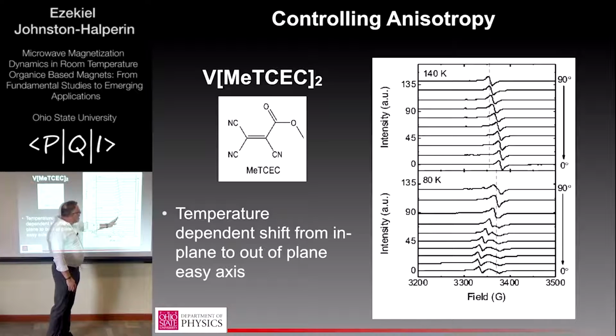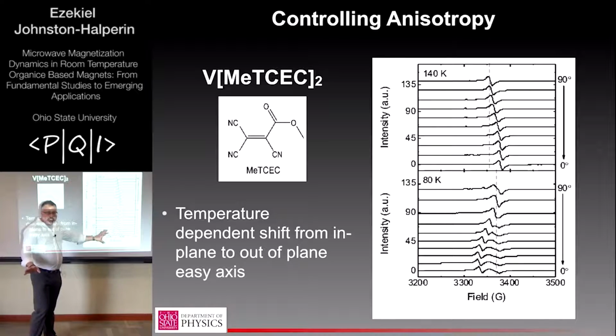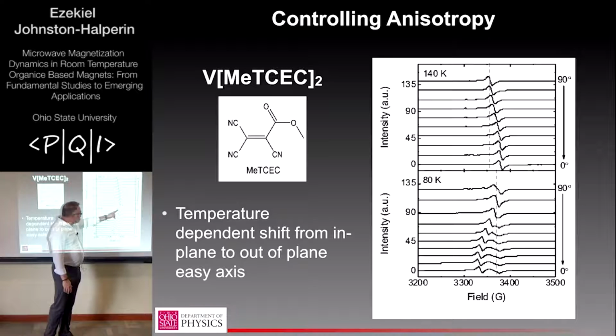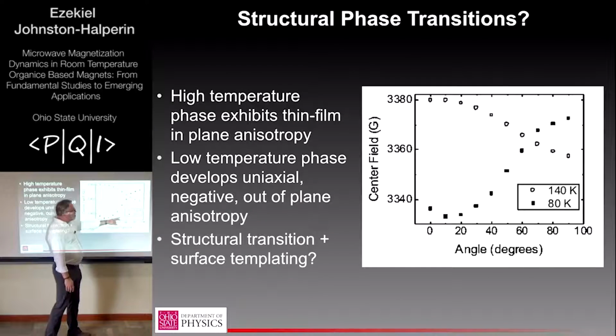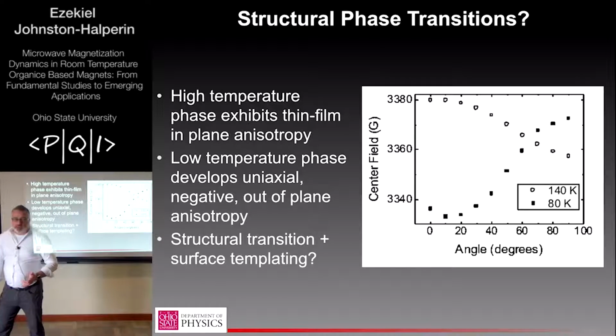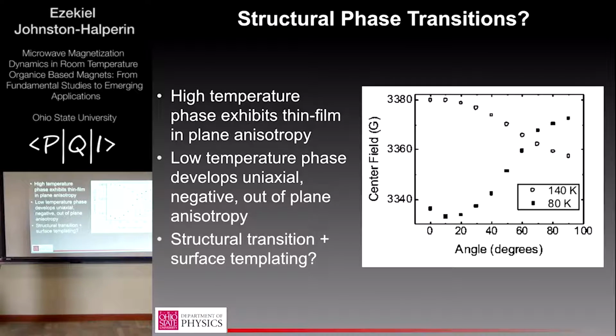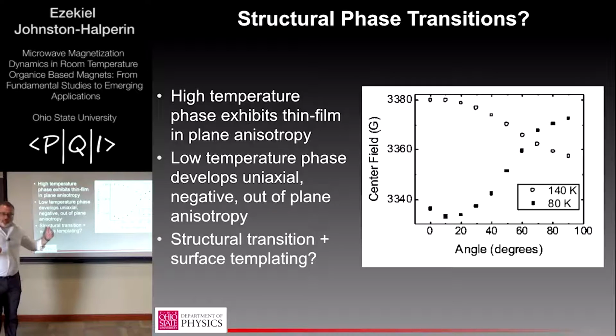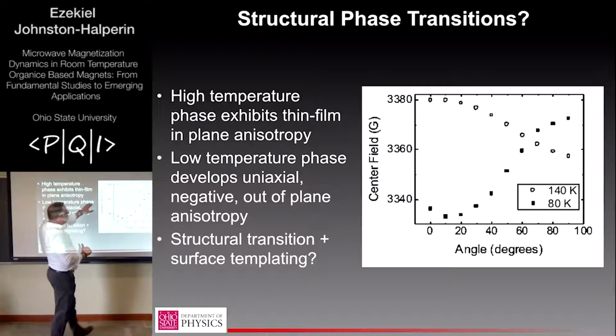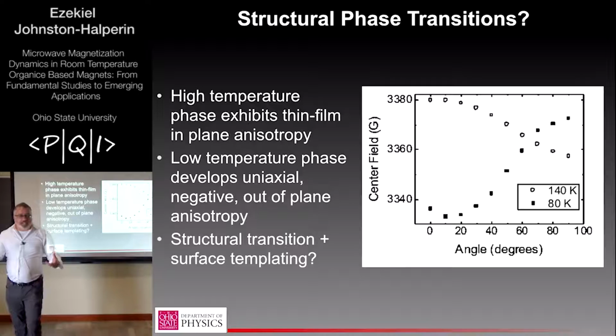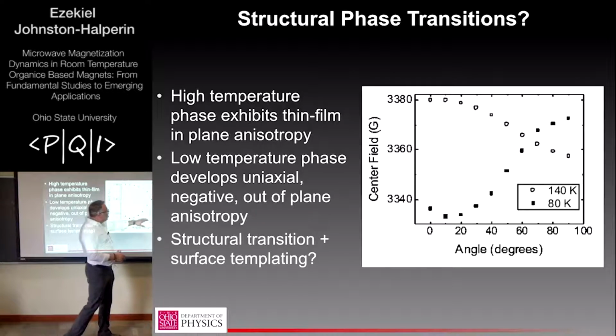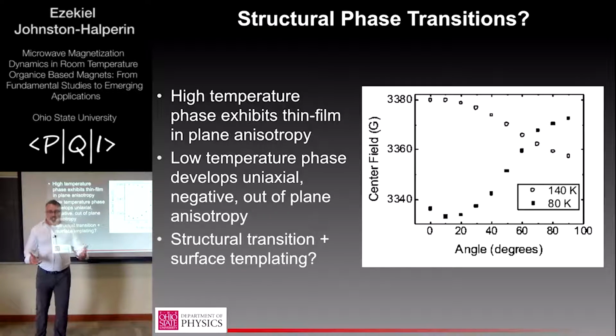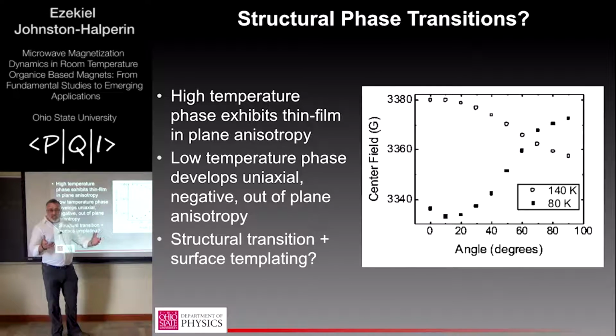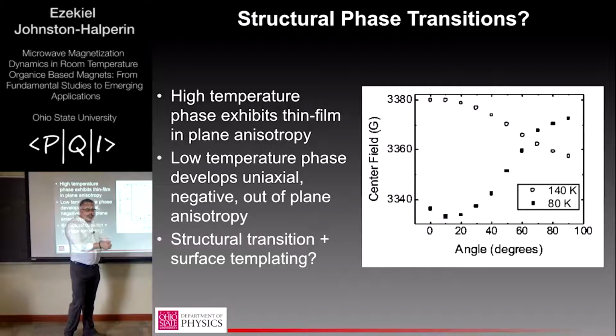But then when we cooled it down to 80K, the spectrum gets messy because this material is messier than BTCNE. That's a separate topic. But you'll notice this trend is now going in the opposite direction. If we track those two behaviors at low temperature and high temperature, you get these phase flipped variations. So what this means is that we've been able to switch the easy axis from in plane to out of plane. Coming back to the intuition we built up from the nanowire study, this means that at high temperature we have some easy axis in plane defined by shape anisotropy. But at low temperature, there's a transition. We think this may be a structural phase transition in the material where a crystal field anisotropy turns on with a different symmetry, so it pushes the easy axis from in plane to out of plane.